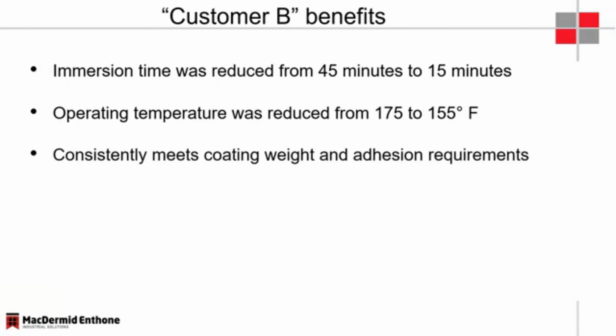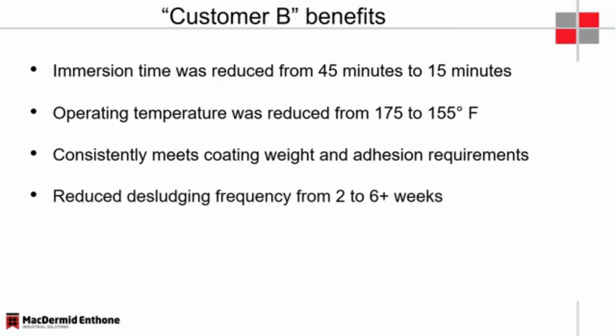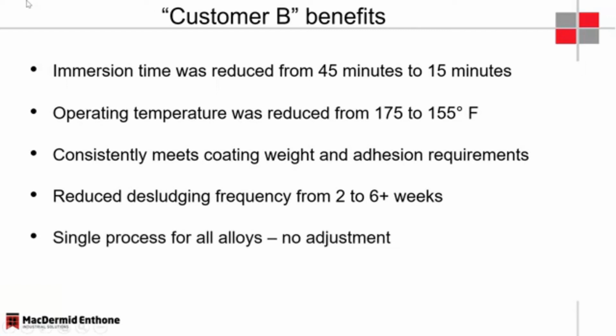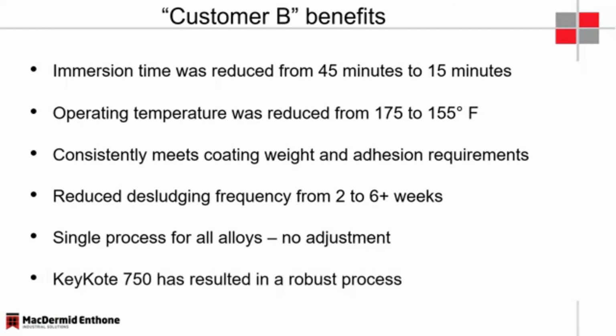The process has enabled them to consistently meet both their coating weight and adhesion requirements across the various alloys that they have to process. And it has reduced the desludging frequency. They had been having to desludge at a frequency of about every 2 weeks. This has been extended out to 6+ weeks. And it has resulted in a process that enables them to use a single process for all of the alloys that they have to process without the need to adjust bath parameters. So after being in place for a year at customer B, the 750 process has resulted in a reliable and robust process for customer B.